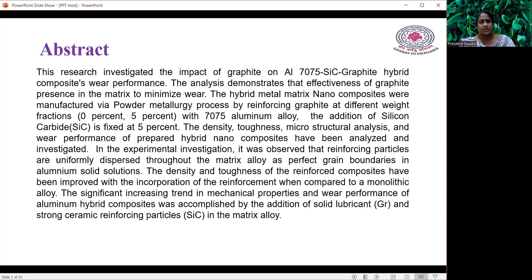In this process, the density, toughness, microstructural analysis and wear performance of the prepared hybrid nanocomposites have been analyzed and investigated. The density and toughness of the reinforced composites have been improved with the incorporation of the reinforcement when compared to a monolithic alloy. A significant increasing trend in mechanical properties and wear performance of the aluminium hybrid composites was accomplished by the addition of silicon carbide and graphite particles.